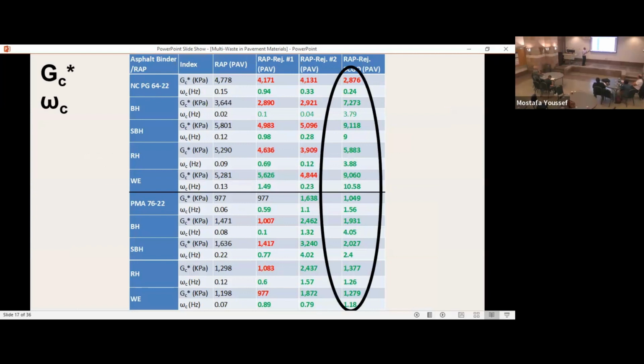If you compare Rejuvenator 1, which is already sold on the market in the US, same with Rejuvenator 2, same with Rejuvenator 3, you will notice that for all the combinations of unmodified binder and the OFA, the off-spec ash, and the modified binder and off-spec ash, the gain is typically in the crossover frequency, because that's what rejuvenators do. They soften the binder. That's most of the time what they do. What we have realized is that we are having an effect on the crossover frequency and the crossover modulus as well.